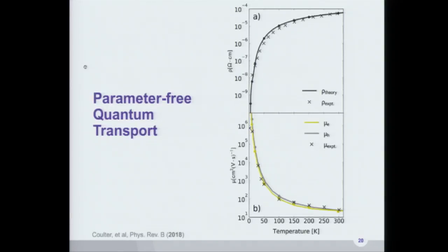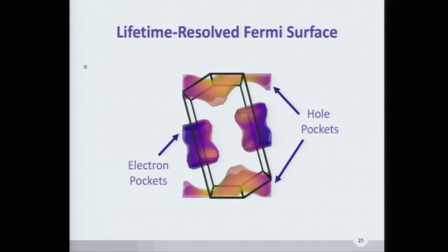So, yay, awesome. This is another result that we compared with experiment, and I was very, very happy when I saw this. The solid line is the theory, and the x's are experiment. This is looking at the resistivity and the mobility. And there is no fitting parameter here. There is no adjustment, normalization, or whatever words you've heard about a fudge factor in the past. None of that. We got the experiments from Johannes Guth. He gave us the data set, and Jenny had the calculations, and they line up. So we understand the quantum transport in tungsten phosphide. And now we're looking to see how general this is for us to understand hydrodynamics in other systems.